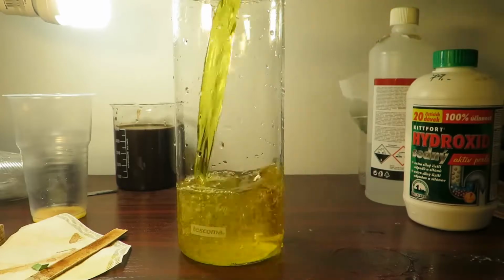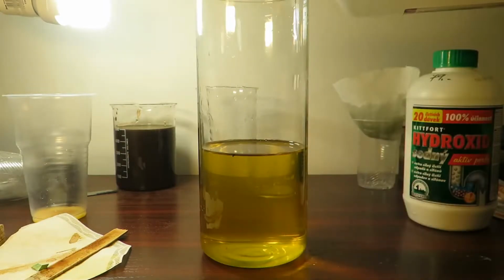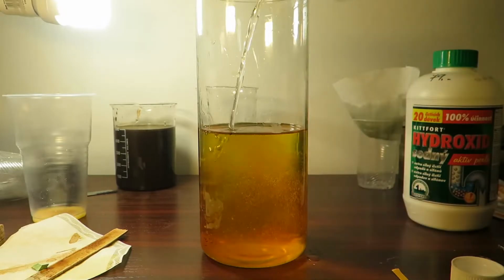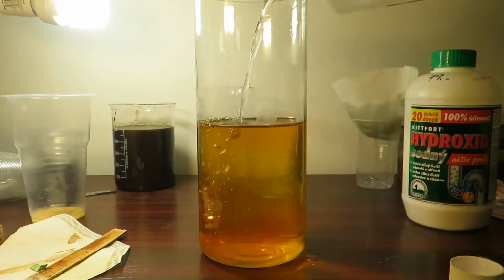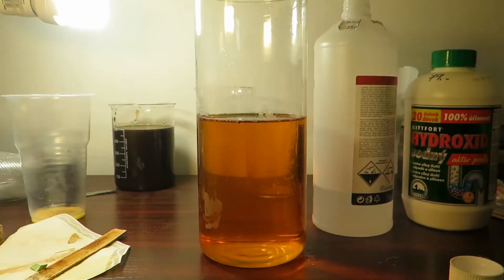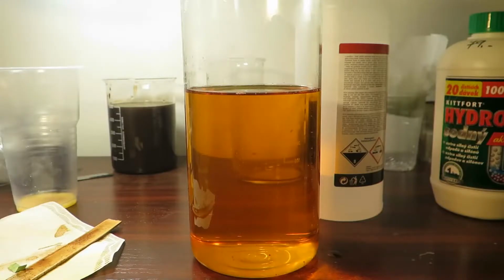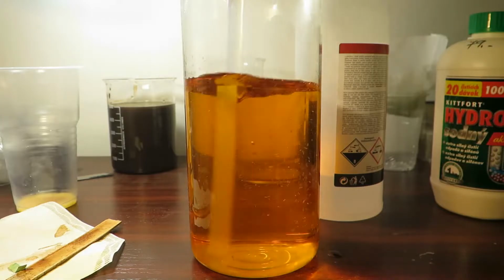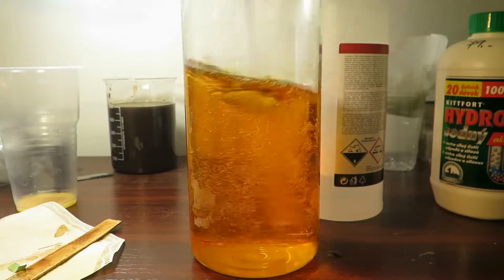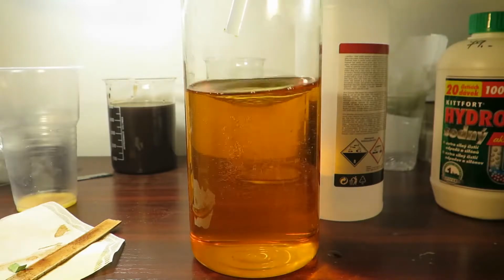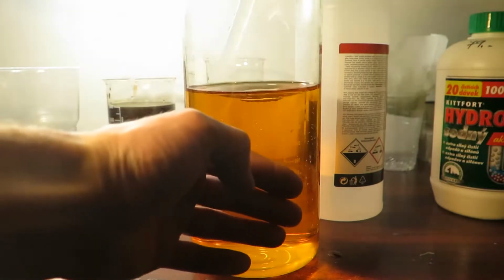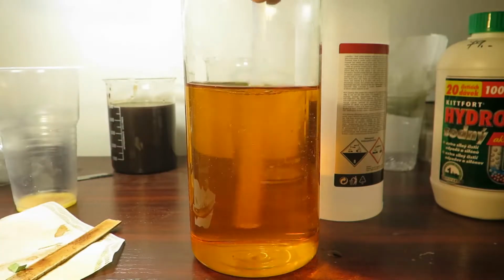Then I transfer the sodium chromate into the hugest beaker, and in the next step of the reaction we will acidify the solution to form sodium dichromate. So the solution will change color from yellowish to orange. Now we want to reduce the oxidation state of the chromium to +3, so it's much safer to handle. Well, we have quite a few options there. This could be done with a primary alcohol such as ethanol, sulfite ions such as potassium or sodium sulfite, or bisulfite, as far as I am aware. I've tried both of these, but it's quite messy, at least with ethanol, and quite smelly with bisulfite.